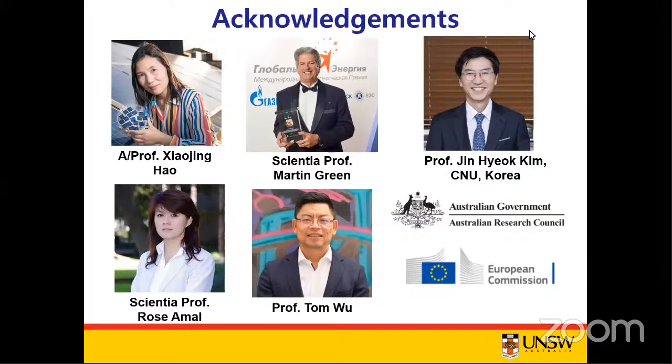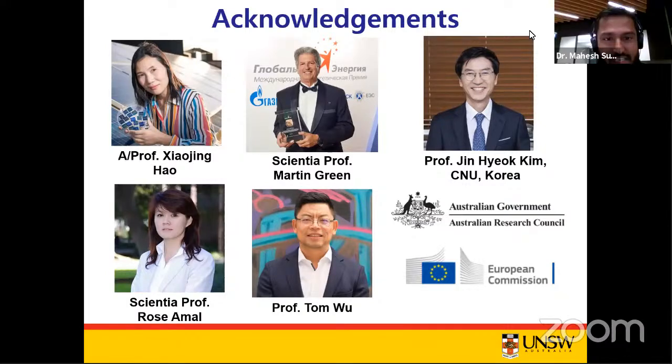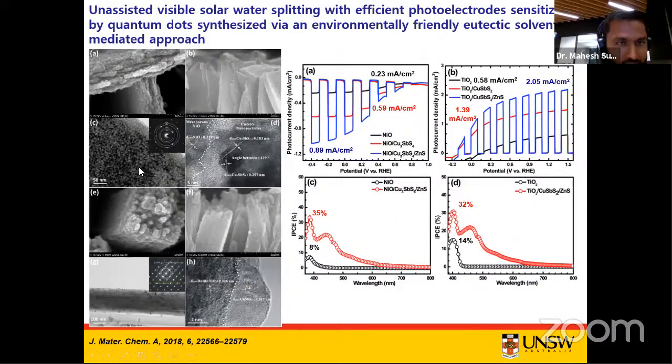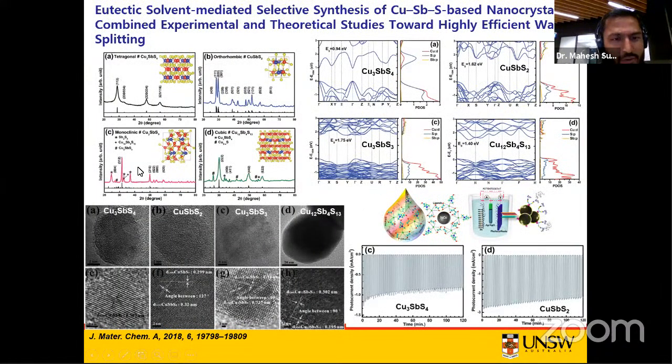What about the nanocrystal size? You can tune the sizes either by changing the reaction conditions, mostly temperature and time, and also by changing the different ligands. In our case, the particle sizes were about 9 nanometers, 11 nanometers, 17 and 20 nanometers. Again, it depends on the different compounds and their properties. But of course, you can easily tune the nanocrystal sizes by optimizing the different preparative parameters.